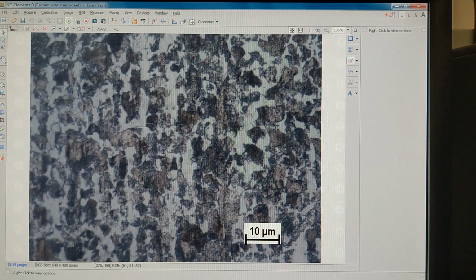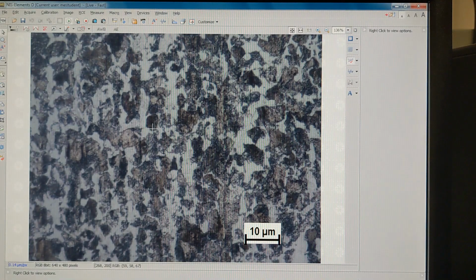So here's some more. Our hot rolling seems to have made our grains more circular in shape, like so. But it also has made them slightly smaller, which is a feature of heat treatment sometimes. It can happen. So when you measure your average grain size, you would likely find that is the case using our lineal intercept method.